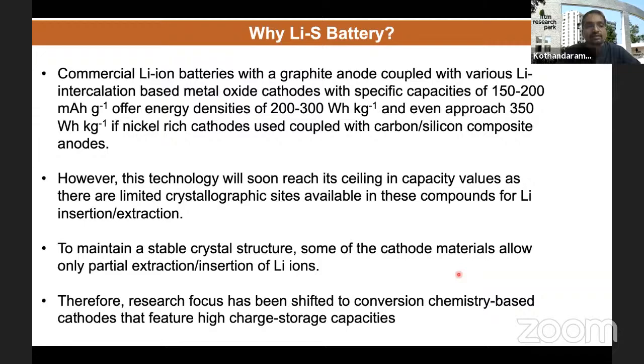So why do we look for lithium sulfur battery, although there are many lithium ion batteries around now? Because the commercial lithium ion batteries can reach even up to 350 watt-hour per kg if nickel-rich cathodes are used. But the common ones are like 150 to 200 milliampere hour, which translates to about 300 watt-hour per kg. But this technology has already reached its ceiling in terms of capacity, because it is based on intercalation chemistry. There are only so many crystallographic active sites available in a host structure. Therefore, the amount of lithium that we can insert and reinsert is limited. Sometimes, as in the case of lithium cobalt oxide, you can't extract all the lithium out of it. Only a part of it can be extracted in order to maintain the crystal structure stable.